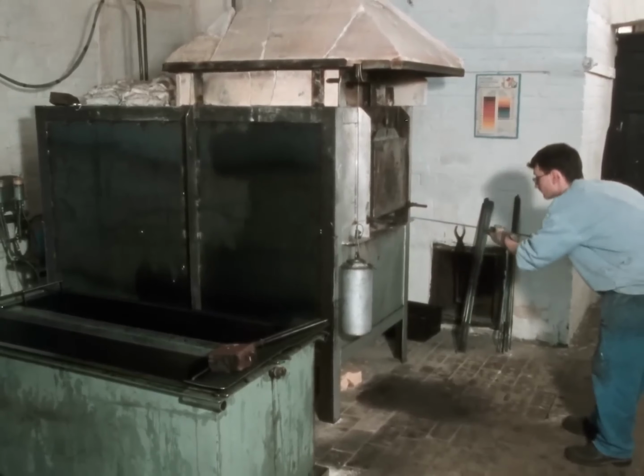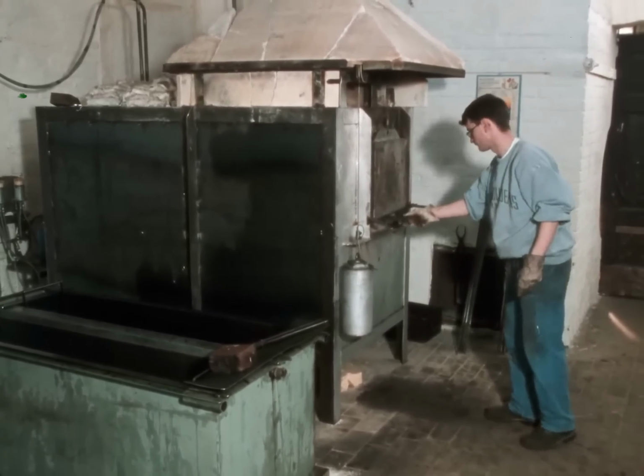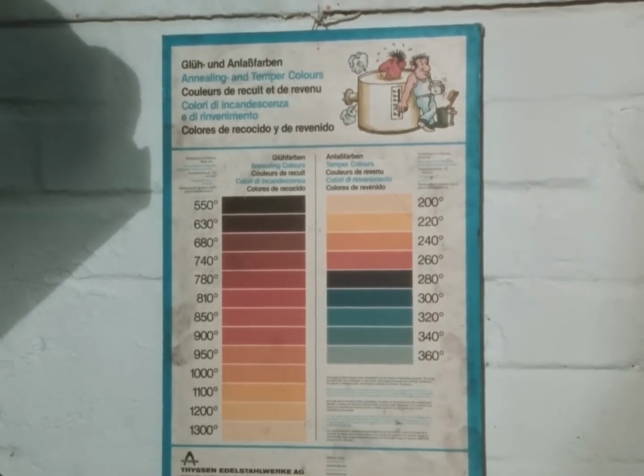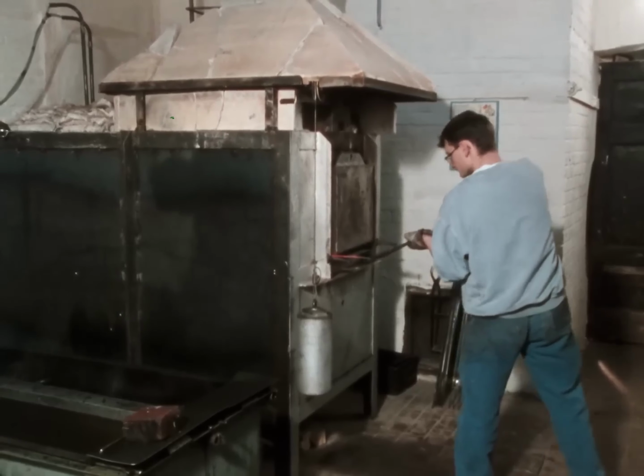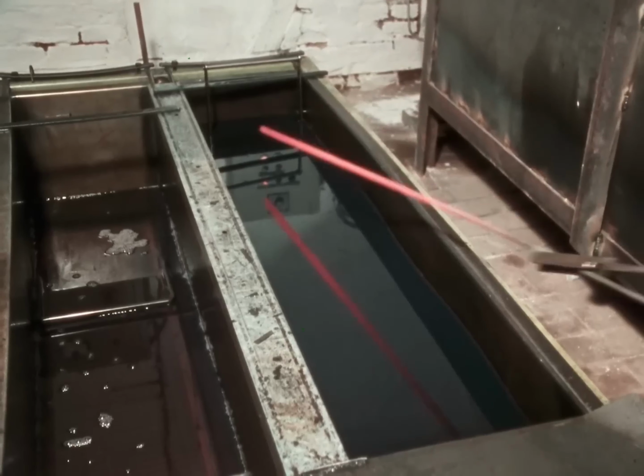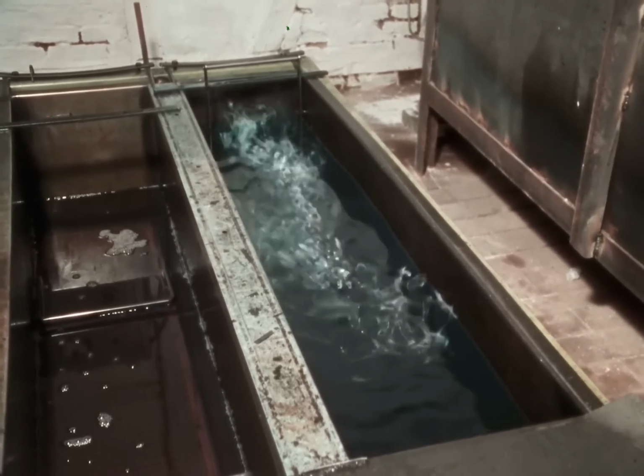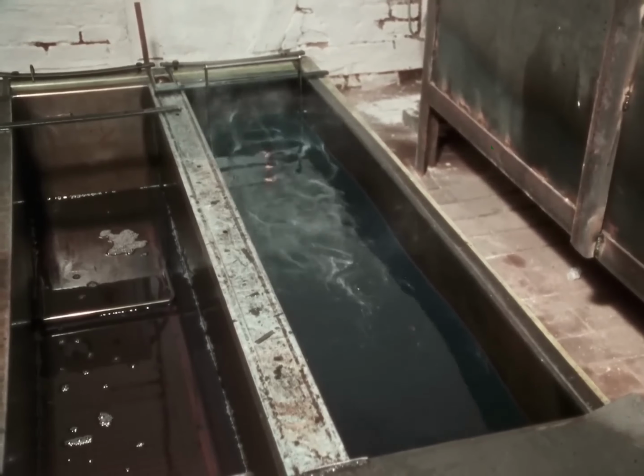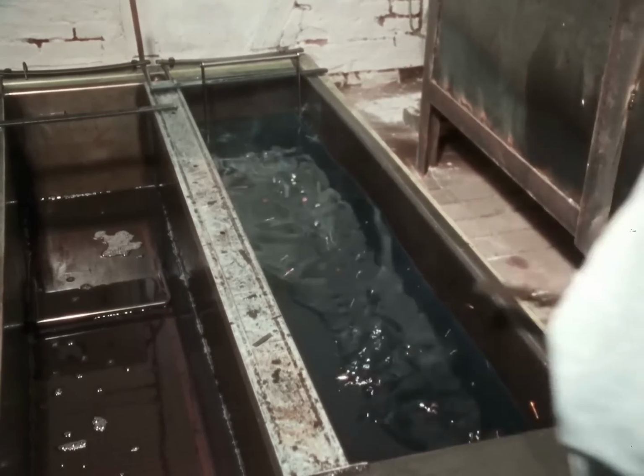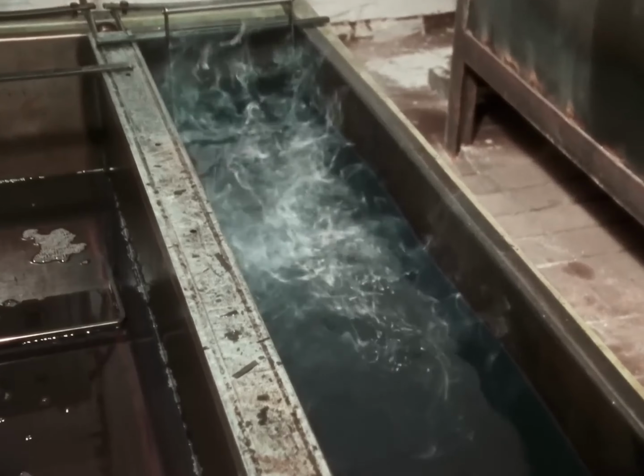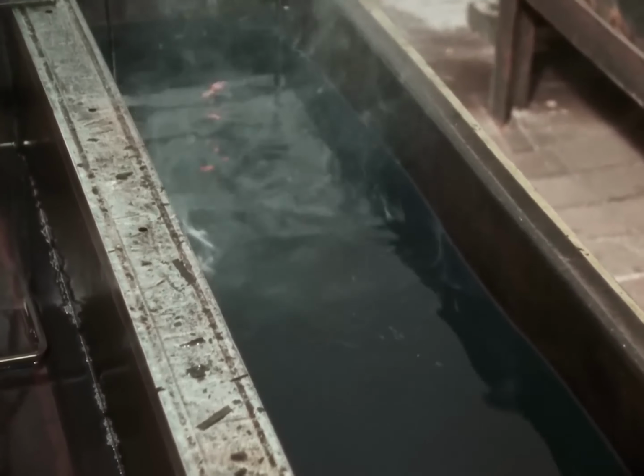Hardening happens in a glow furnace at a temperature of roughly 890 degrees Celsius. From there, the blade goes straight into a quenching bath, oil, in this case, though water serves the same purpose in other shops, and the sudden drop in temperature locks the steel into a harder, tighter internal structure than it had before. The goal isn't uniform hardness throughout, though.